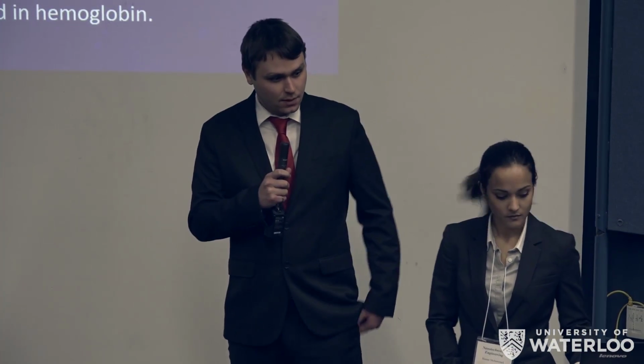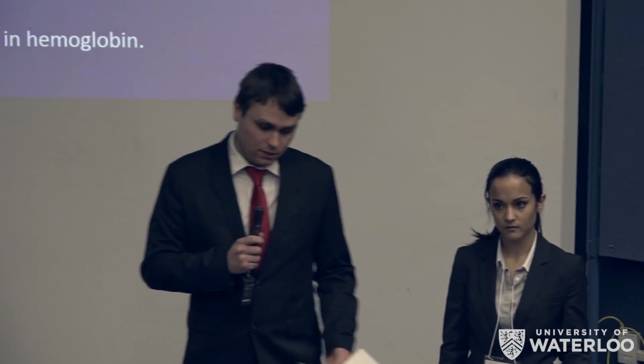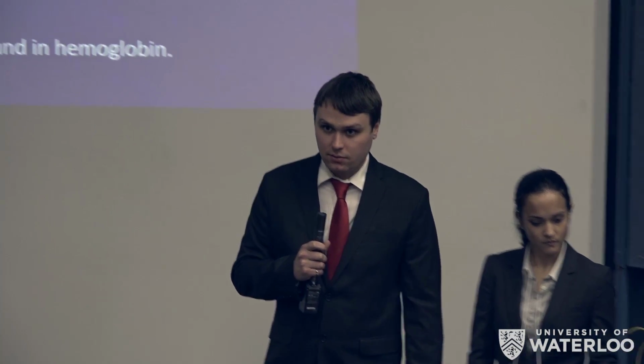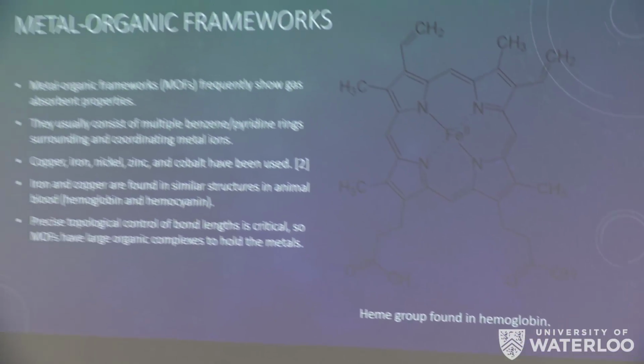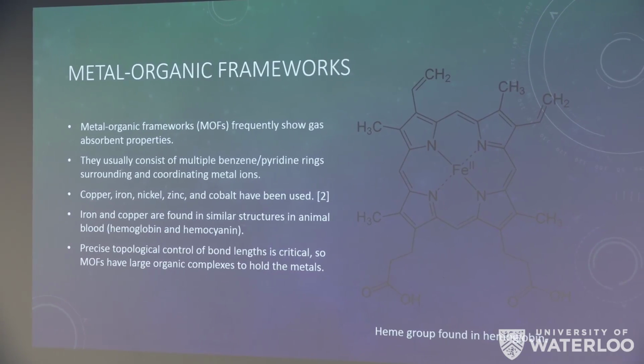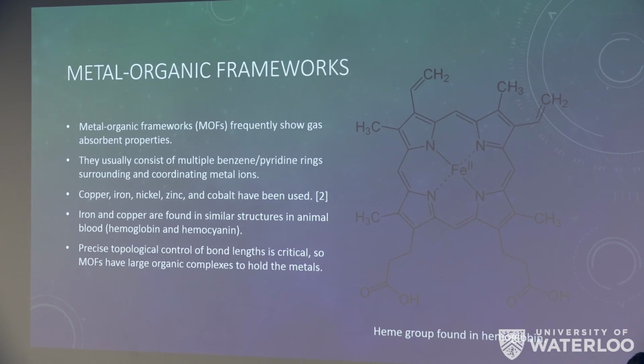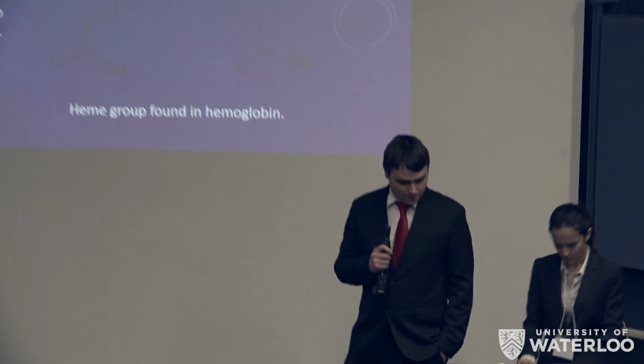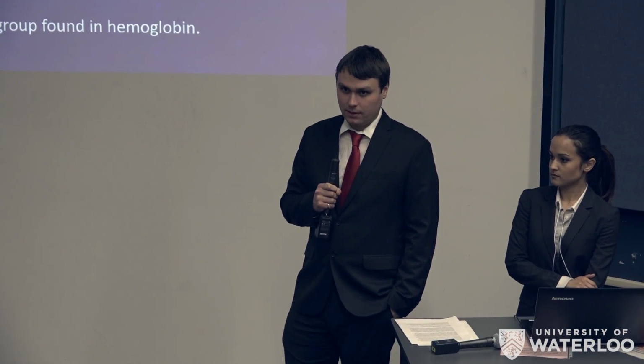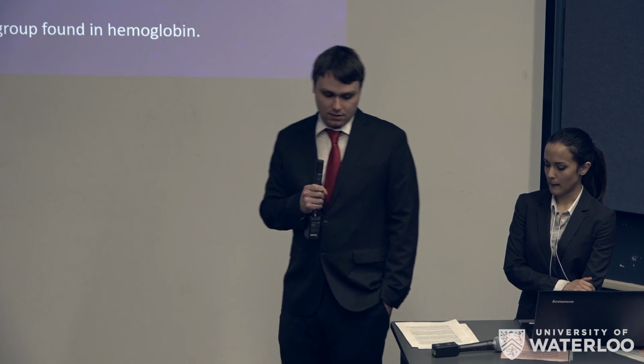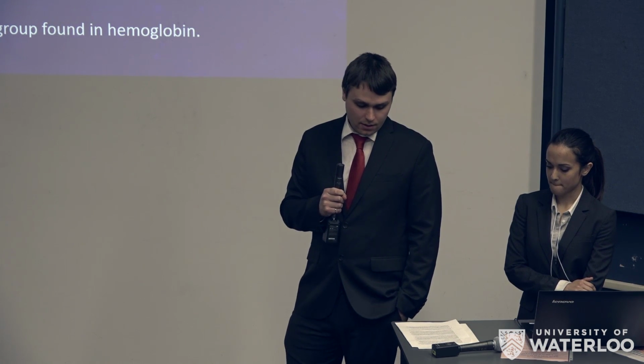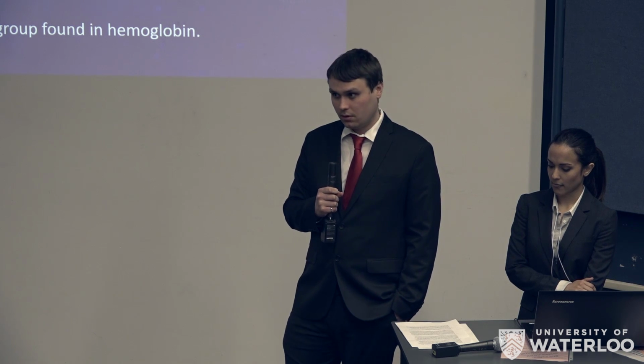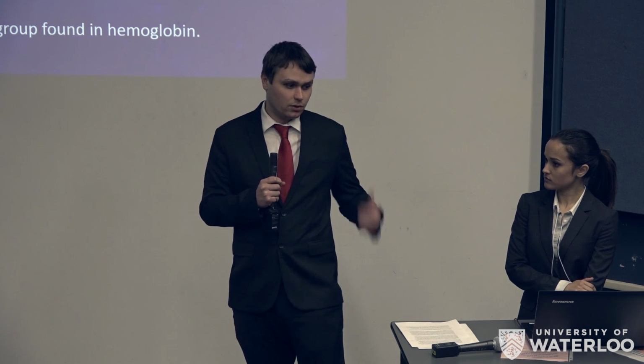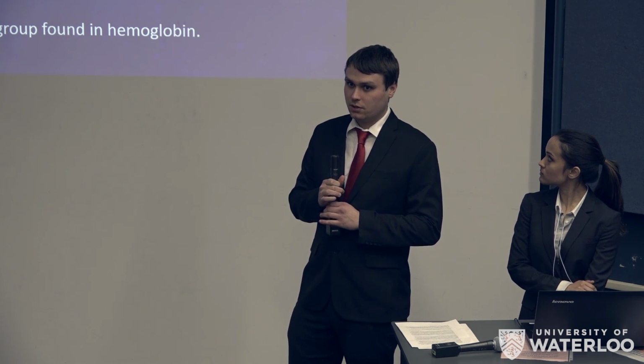At this point, it's necessary for me to introduce metal-organic frameworks. A metal-organic framework is a large macromolecule which contains 1 to 4 metallic centers surrounded and coordinated by a large organic structure. This organic cage is usually a complex of large carbon-based ring structures coordinating this metal center. They're often capable of reversible diatomic gas absorption, and this property has made them the subject of much research recently. They are also found in nature. For example, the heme group in the hemoglobin of our blood, shown above, is essentially one of these structures using iron as the core.